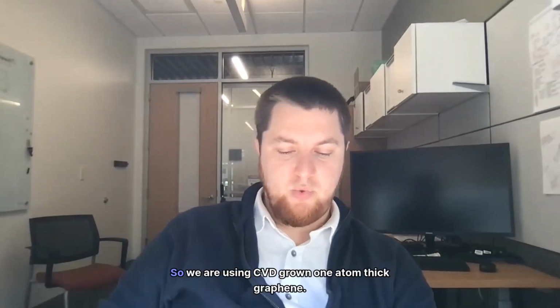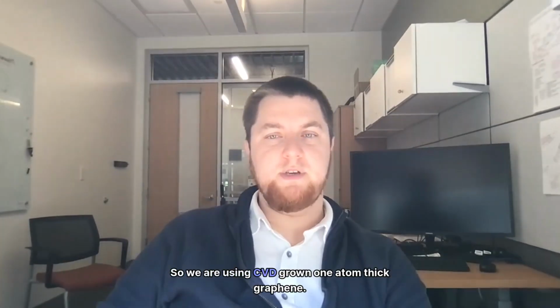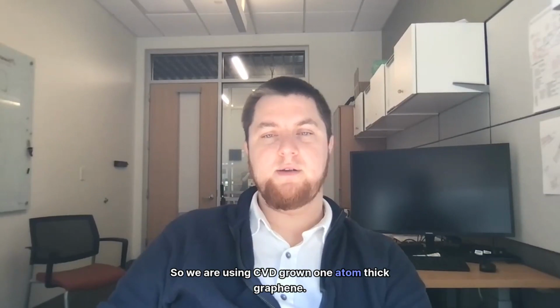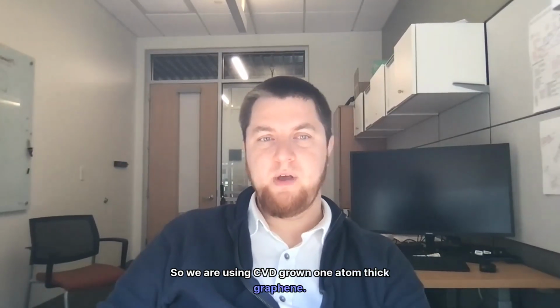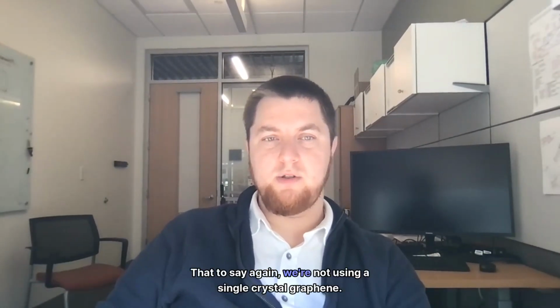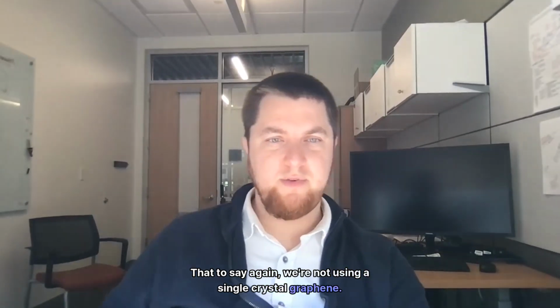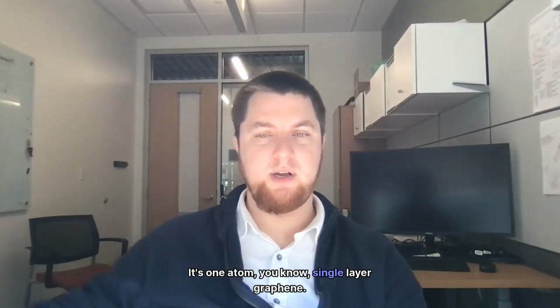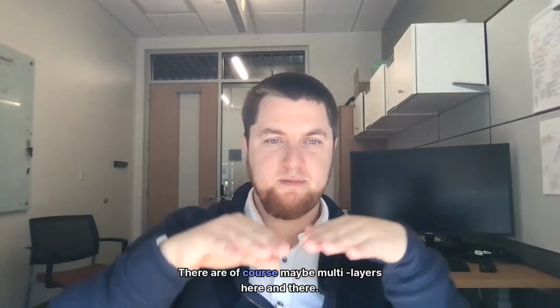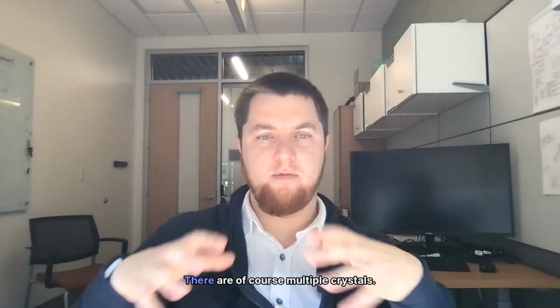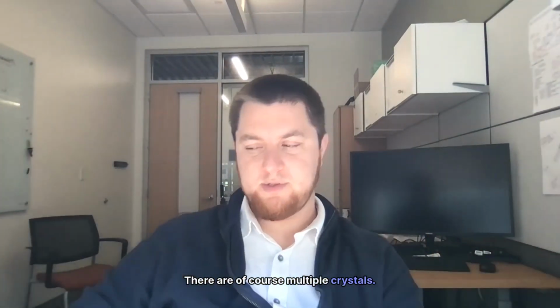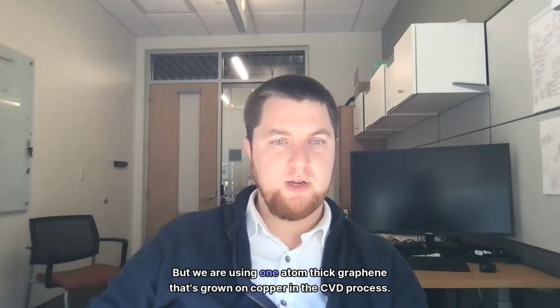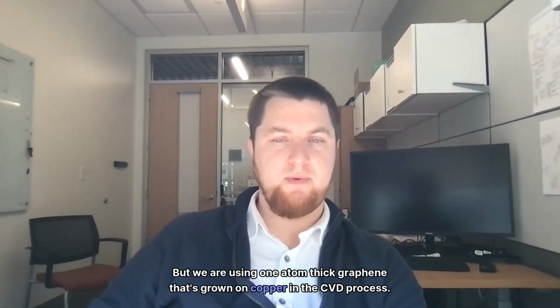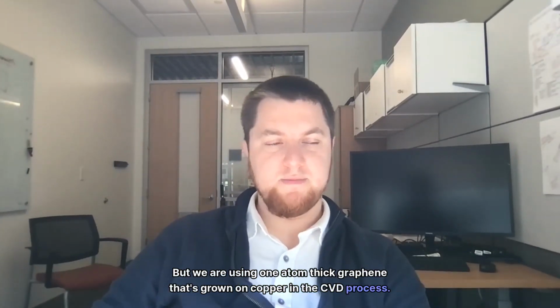Right. So we are using CVD-grown one atom thick graphene. With that said, we're not using a single crystal graphene. It's one atom, single layer graphene. There are of course maybe multilayers here and there. There are of course multiple crystals. But we are using one atom thick graphene that's grown on copper in a CVD process.